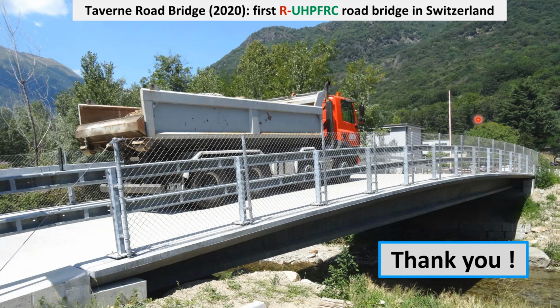Then, can you describe curing needs for control of shrinkage cracking considering the high release strength? Curing is very similar to curing of other cementitious materials. Apply immediately a curing compound, and then plastic foil or thermal isolating mat, depending on the outside temperature, of course. The duration of curing is given as a function of the outside temperature. It's probably a bit conservative for UHPFRC, but we do not want to take any risk. The result is very good. We have no shrinkage cracks. How many days of curing are needed? Typically, it's 3 to 4 days.